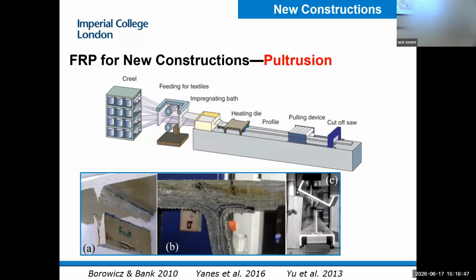So when we had this material, researchers in civil engineering were very happy and wanted to replace steel elements using FRP. However, when they did structural testing, they noticed premature failure at the cross section. For example, testing a beam, the load is perpendicular, transverse to the fiber direction, so they never achieved the material capacity before premature failure. I call this web crippling.